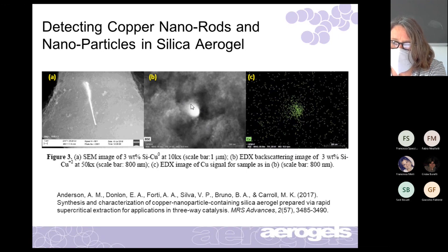These nanoparticles, think about what size they were. So this scale is 800 nanometers. So this diameter maybe 400 nanometers. But we put in particles that were much smaller than that. So this is telling us that we are getting agglomeration, where the particles are all collecting together, which is not necessarily what we want, but it's what we have.